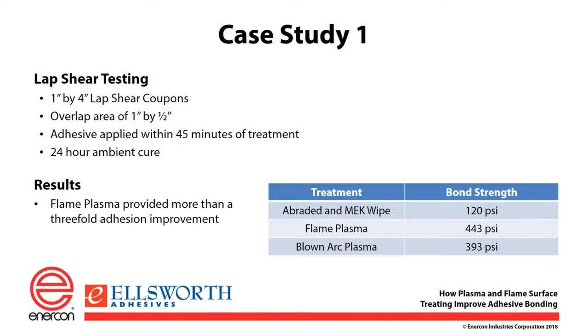The test that was done is a 1-inch by 4-inch overlap of the lap shear coupons, and the adhesive was applied within 45 minutes of the treatment of the substrate. The material was allowed to cure for 24 hours under ambient temperatures, and you can see that the abraded and MEK wiped polyethylene gave a 120 psi bond strength. Flame plasma increased this to 443 psi. And blown arc plasma increased it to 393 psi.